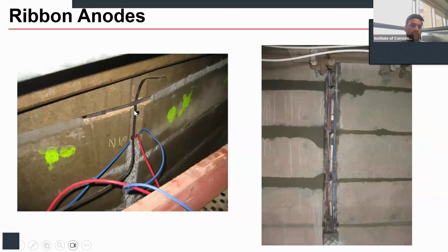Then we have these ribbon anodes, again surface embeddable. We cut a small chase on the concrete surface and embed these MMO ribbons. You can hold them in place using plastic pins. The feeder cable, generally a titanium strip, connects all these ribbons together, and then this goes to the rectifier systems. A cementitious overlay is then used to fill this chase.